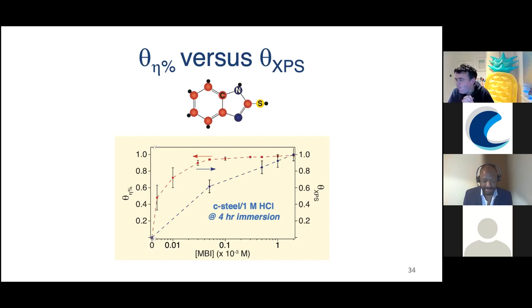Okay, perfect. Next question, hopefully a quick one. How is CMC determined? CMC was determined in this case using a tensiometer, where you basically pull out the liquid and form a drop, and it determines how much tension there is at this point. So you get a plot where it decreases and then flattens off. There's various ways of doing it, but that's one way. We also have tried dynamic light scattering to see the formation of the micelles. That is more tricky, as it turns out. And we used the surface tensiometer normally for this work because it was straightforward to do. Yeah, makes sense. Keep it simple.